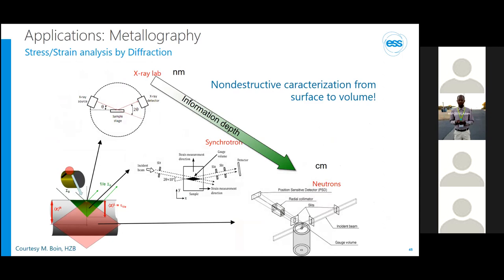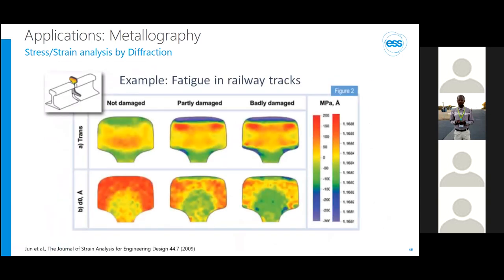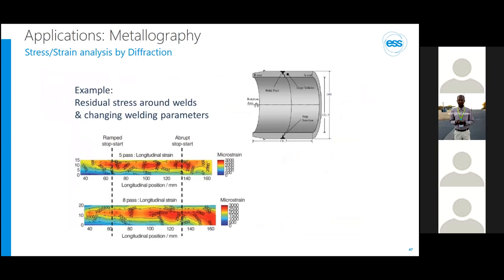and geometry. And then you can map out, for example, complete railway tracks and obtain these residual stress maps of railways and look where maybe damage has occurred. Or you can study and optimize welding parameters, and you can even bring a welding machine to a beamline and do this in situ or however you wish.